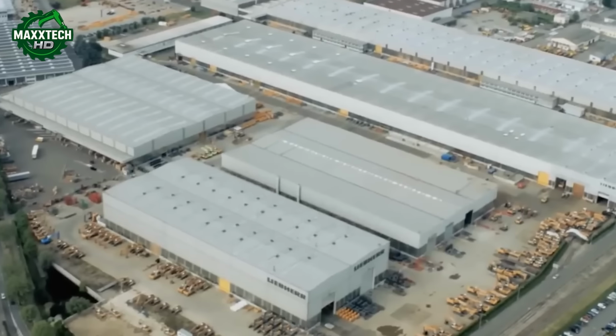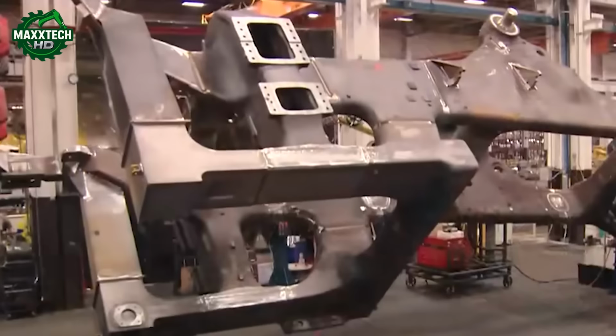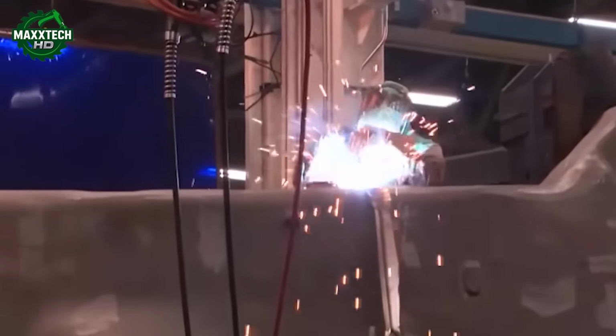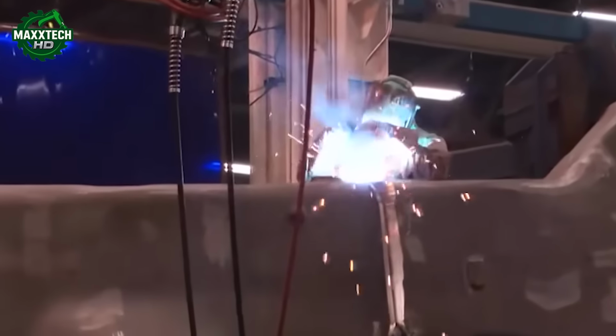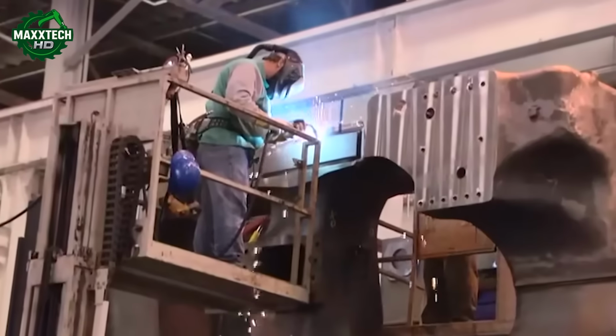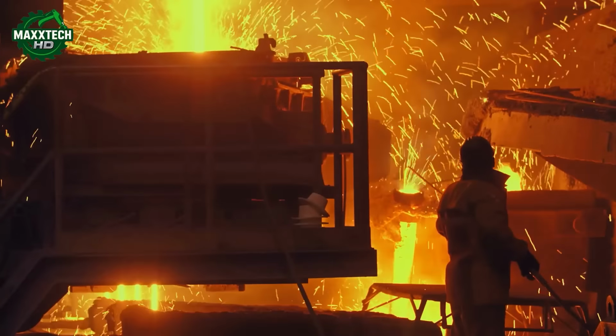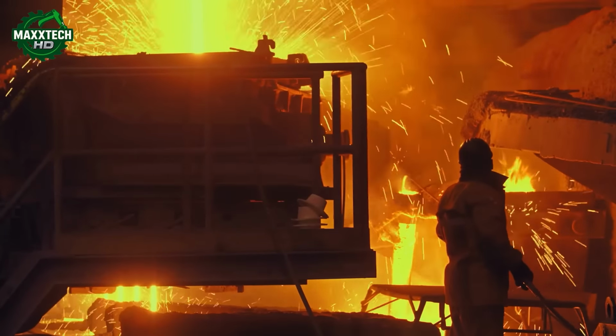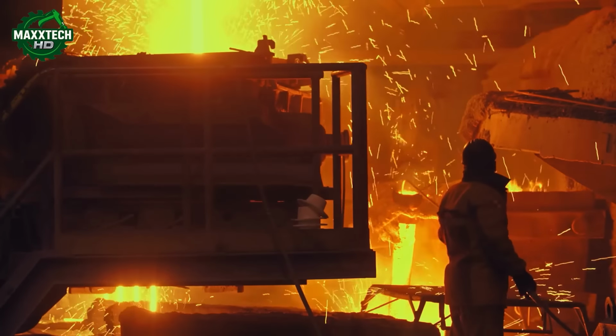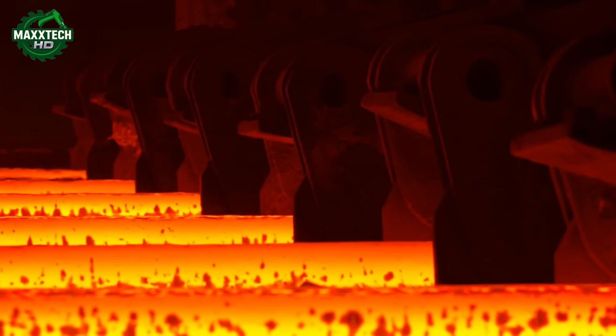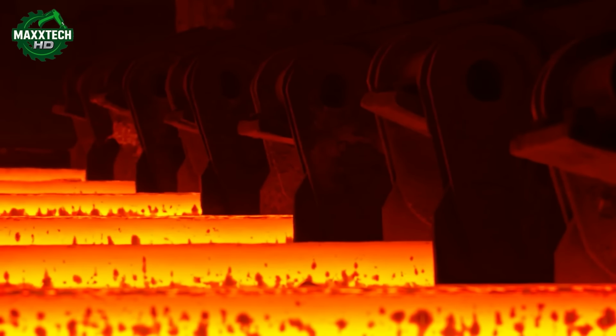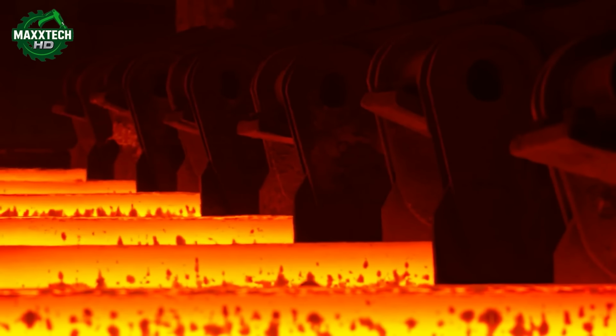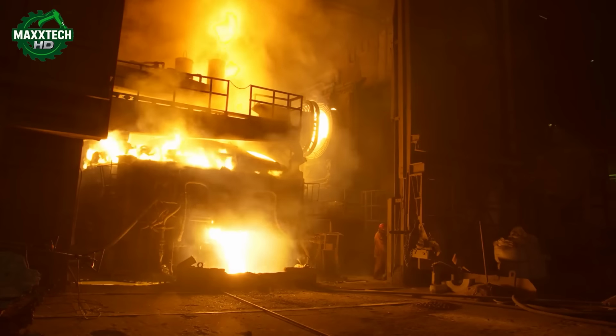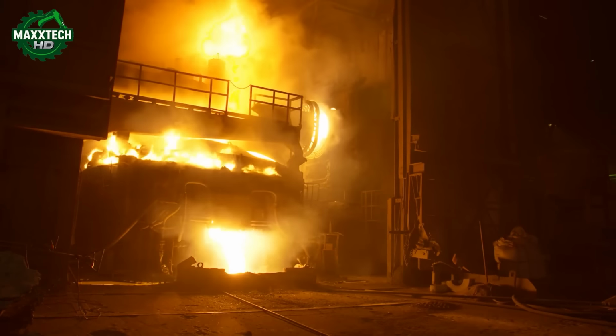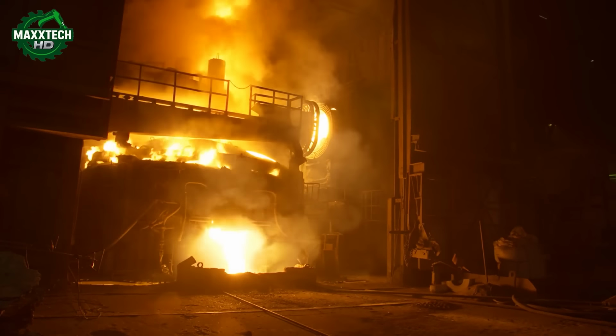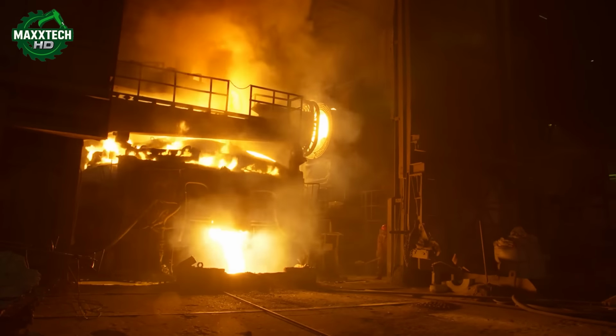At Amite, the crew begins with the center casting, the piece that supports the truck's colossal payload. The process starts with molten metal, heated in the star of the show, a 45-ton arc furnace. Operators fill it with scrap metal, then lower 3 highly charged electrodes into the chamber. As soon as the electrodes touch, a scorching 3,992 degrees Fahrenheit electric arc melts the metal into a bubbling, glowing river.